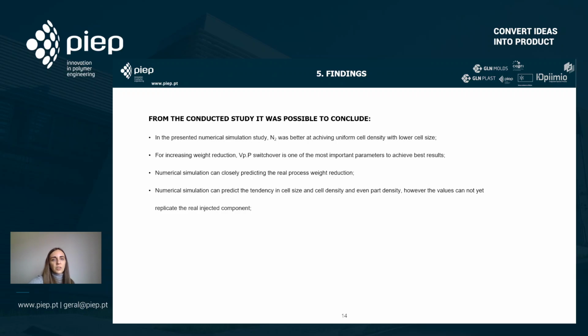So from our study, it was possible to help select which gas was better for our part without having the necessity to produce this part and evaluate each part and characterize and do some tests to determine which gas was going to be better for us. And again, for increasing weight reduction, we could see that the best result was the velocity point switchover. However, we could also see that we have to carefully analyze these results with cell size and cell density.